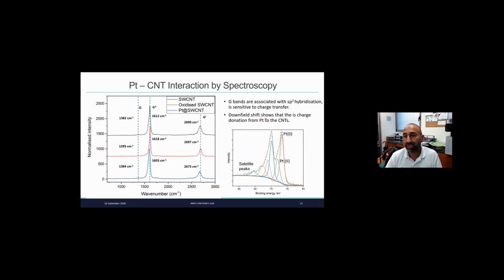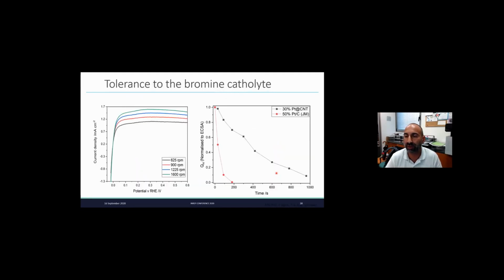So we see that we have some charge transfer from the platinum to the carbon nanotubes, which could also help for the catalysis. The state of the platinum is platinum 0, platinum 2, so slightly oxidized on top. And the nice thing about these nanotubes is that they are very stable with time.